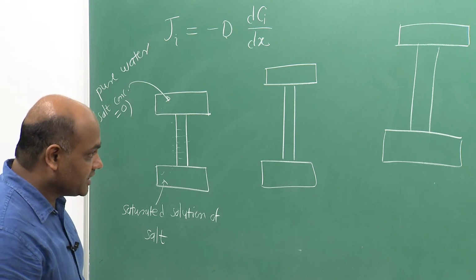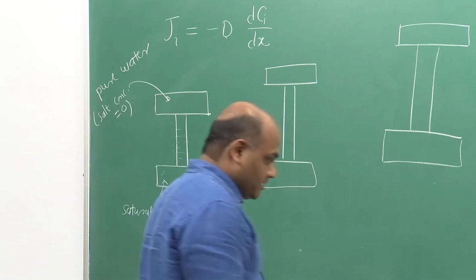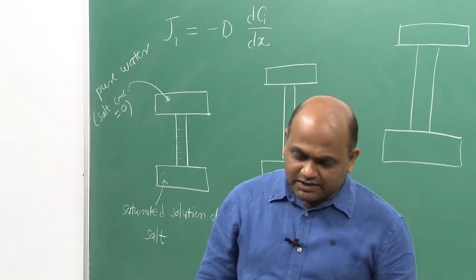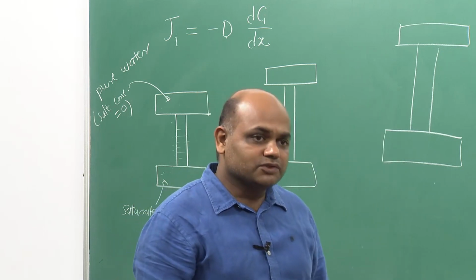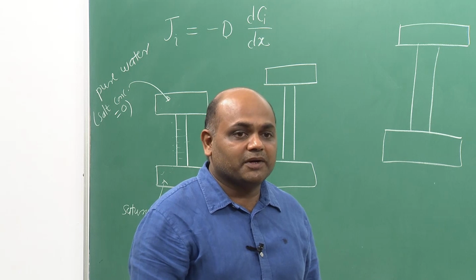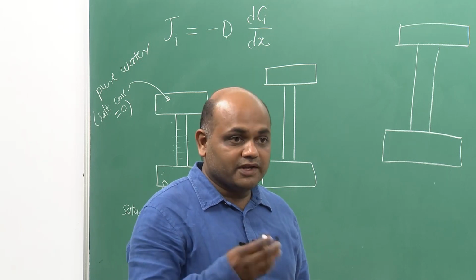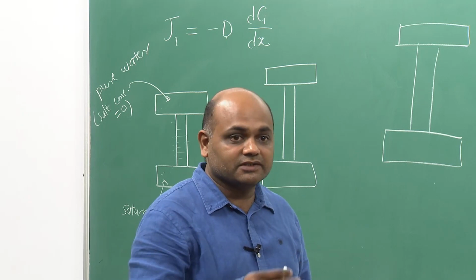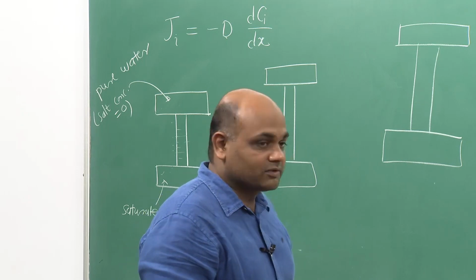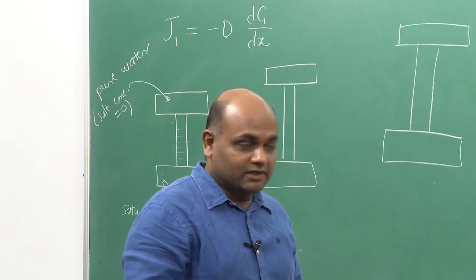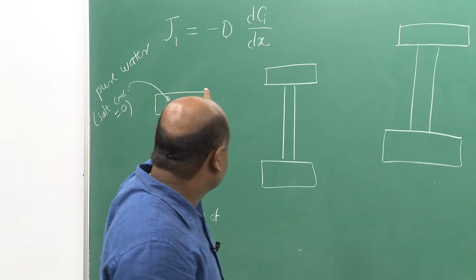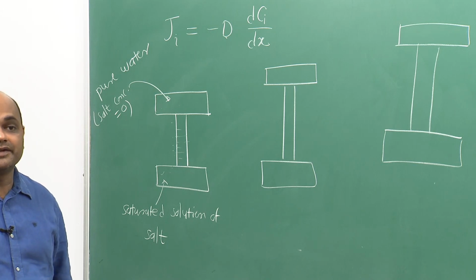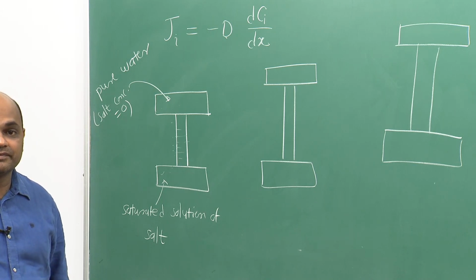So, what he did, he studied diffusion of different elements in liquids, and he also conducted an experiment of diffusion of gold in solid lead. He measured the concentration at different x coordinates in his diffusion experiment, and then applied this Fick's law and measured the diffusivity of gold in lead. Okay.